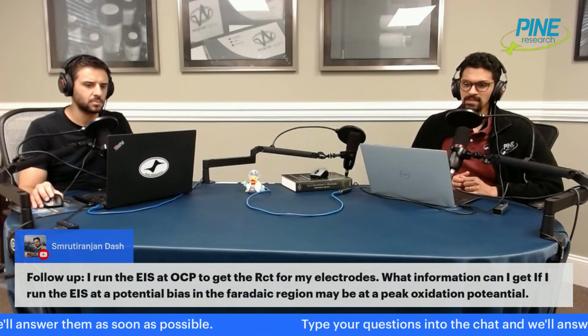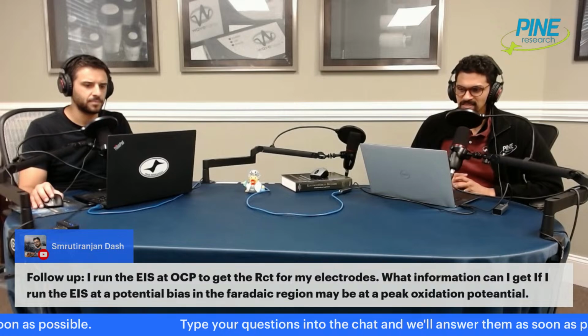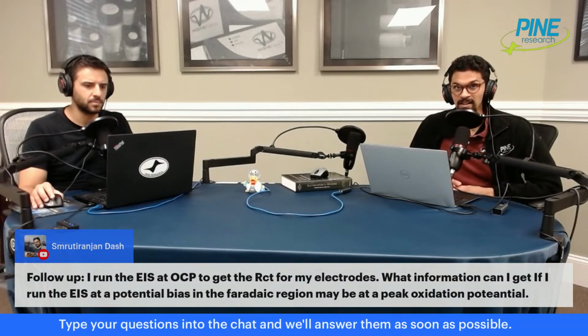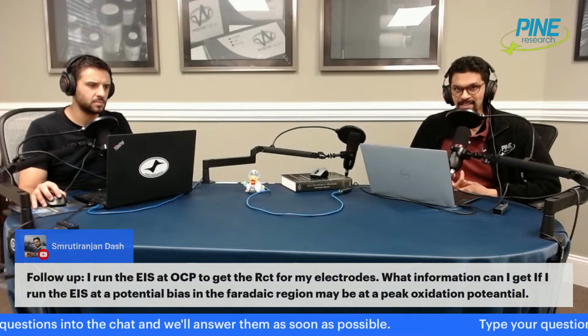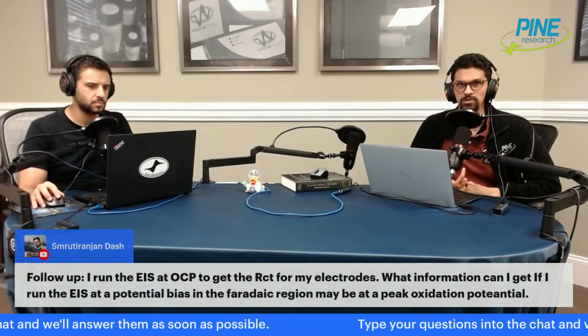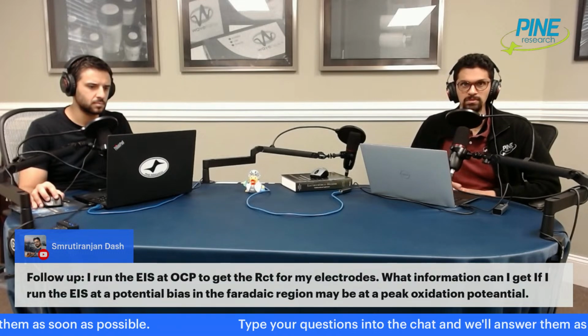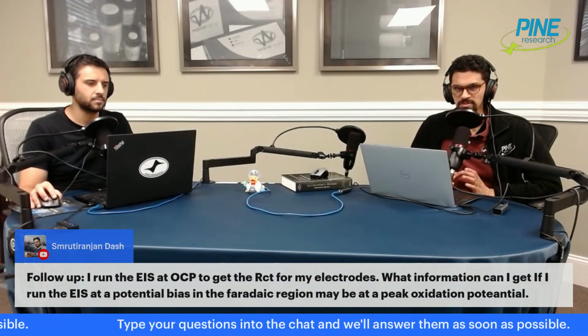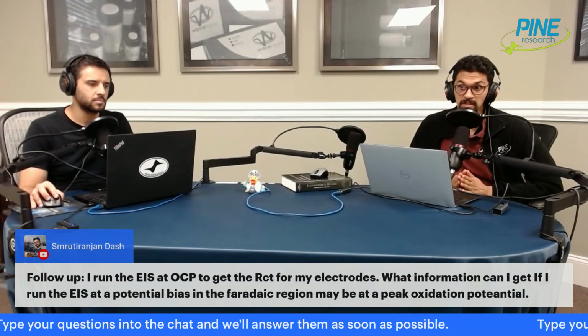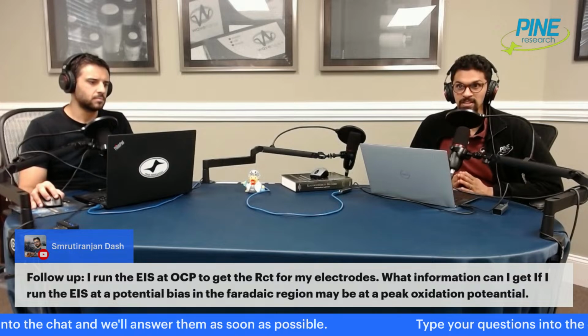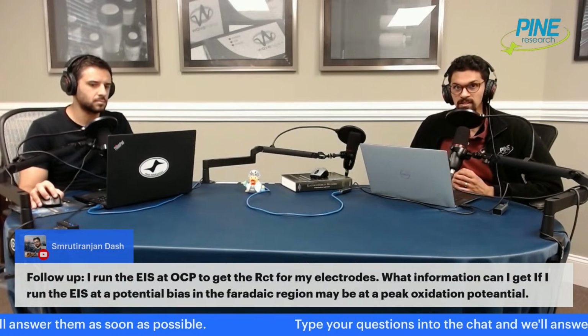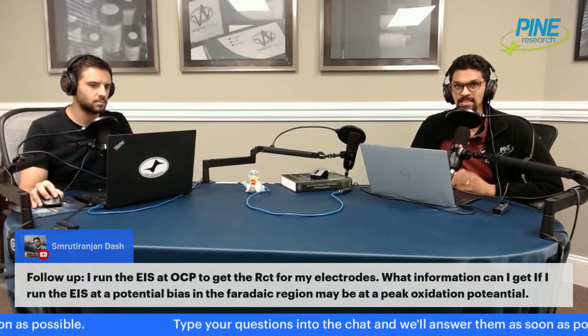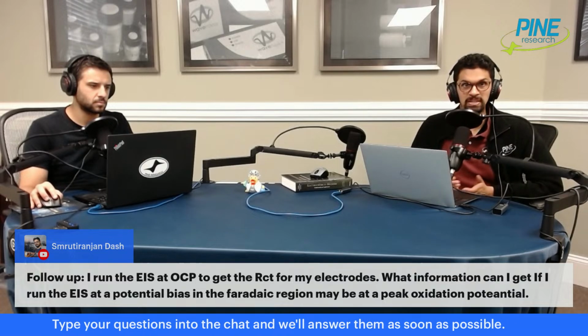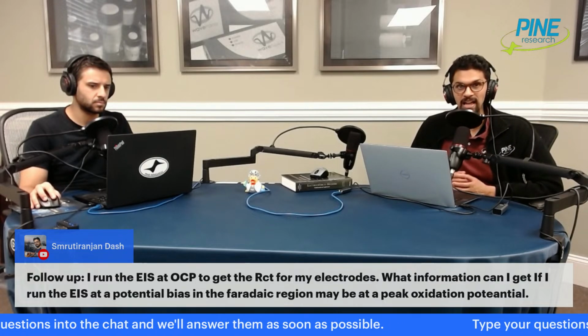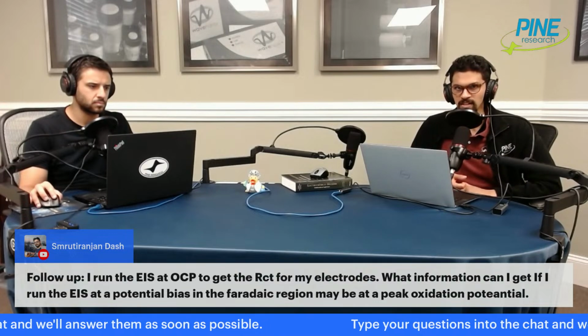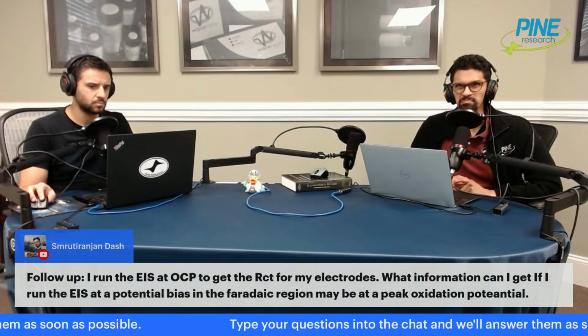So all that being said, it actually makes sense to do EIS at the faradaic potential. You want your system to be stable, linear and causal. So you need to make sure that your system is stable, but at that potential, you let the system run for a while, and then you run EIS at the potential where the peak is, that's the E naught of your reaction.